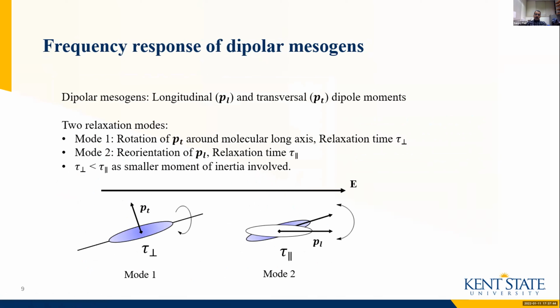In our liquid crystal elastomer system, we have dipolar mesogens, as I mentioned, that interact with the AC electric field. If we apply the field E along this direction, and the molecule has a dipole moment P and is tilted at a small angle, it shows two components of dipole moment, the longitudinal PL and the transverse dipole moment PT. There are two modes possible in our frequency regime. Mode 1: the transverse component PT can rotate around the long molecular axis, and this gives the perpendicular component of relaxation time. In the other, the longitudinal component PL reorients with the field, giving the relaxation time tau parallel.